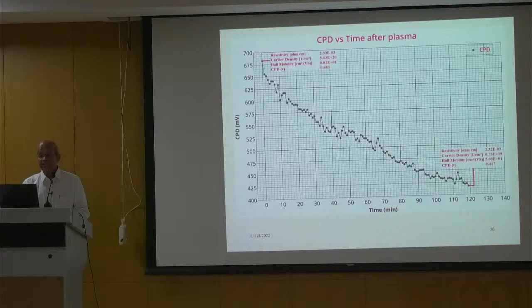Now, at the beginning of this, we measured from Hall measurements the resistivity. It is of the order of 2.33 into 10 to the power of minus 3 ohm centimeter, and the carrier density is about 5.6 into 10 to the power of 20. These are all electrons, and the Hall mobility is about 8.81 centimeter squared per volt second, and CPD is 0.683 volts or 683 millivolts. Within 2 hours, the contact potential difference has come down from 683 millivolts to 417 millivolts, and the carrier concentration has gone from 5.63 into 10 to the power of 20 down to 6.7 into 10 to the power of 19. You can also see the other parameters. The Hall mobility also has changed from 8.8 to 5.03.